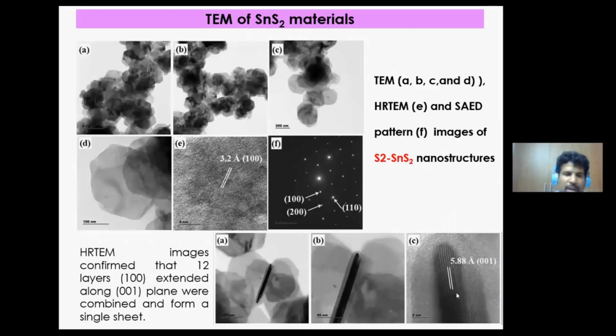It is composed of 12 atomic layers, so we can see the layers that compose a single layer. The outside of this material is due to surfactant. So if you consider only the inside of the structure, we got a beautiful layer-by-layer structure. We counted 12 layers that form one thick disk. That is not a disk; it is a flat two-dimensional SnS2 sheet, a nanosheet.